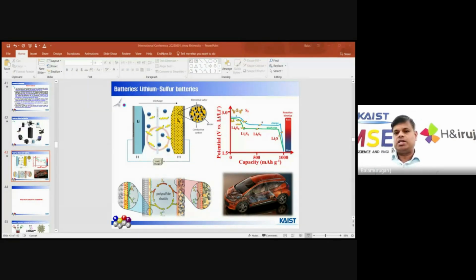But there is one issue because of lithium polysulfide formation. To avoid the polysulfide formation, we need to fabricate a catalyst-based material with higher durability. During discharging, you can see S8 converted to Li2S8, Li2S6, Li2S2 and Li2S, and Li2S6 has to be reversible. Suppose Li2S makes a solid material, it's not reversible, then the battery will die.